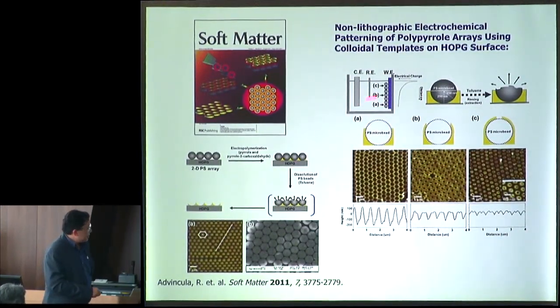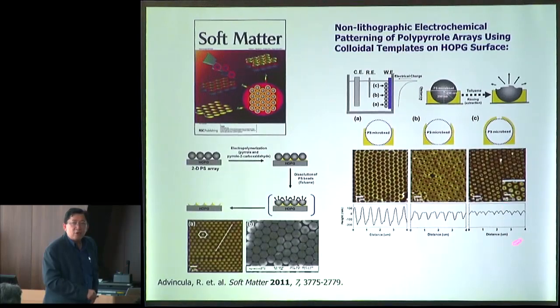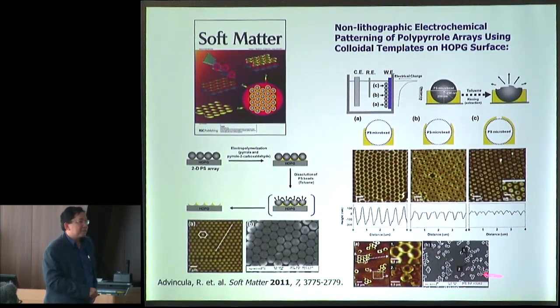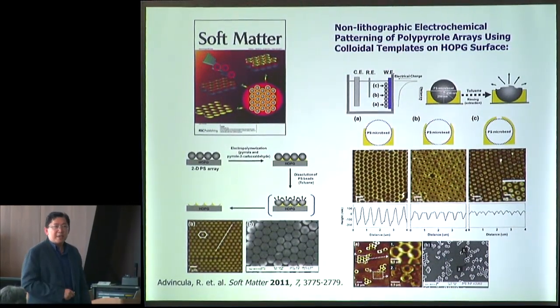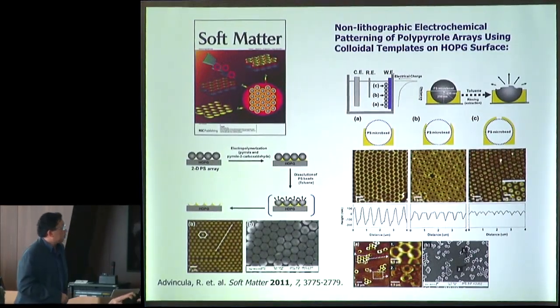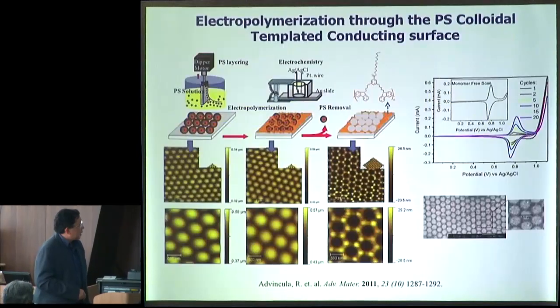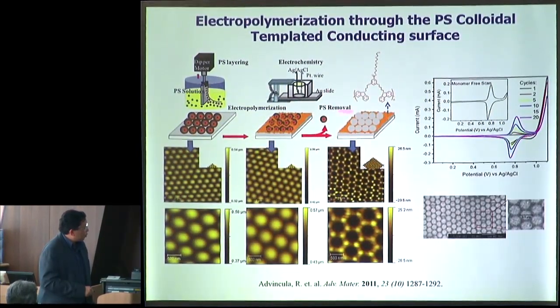We can make a beehive-like structure, a half-dome-like structure, or a full dome structure. In fact, it is so interesting because this full dome structure, we can harvest them as particles, okay? Simply by delaminating them from the surface. So in fact, this may be another way to make colloidal particles based on non-lithographic methods. At any rate, what's interesting is we can electropolymerize conducting polymers underneath. And so this is a pattern of polycarbazole that was electropolymerized. And then after removal of the colloid particle, you have actually a conducting polymer array on an ITO surface.